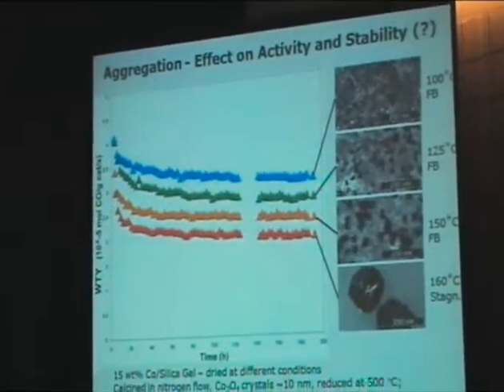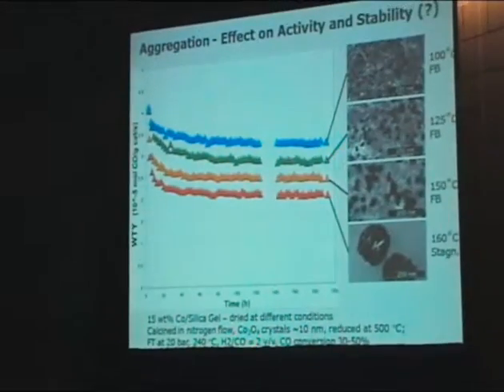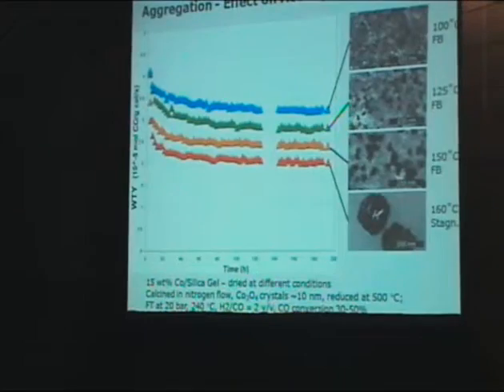Well, since we applied a quite severe reduction, this may be an impact via the reduction rather than the catalysis. However, it also seems that the most significant deactivations are apparent with the catalyst with the lowest activity. And that's something that intrigues us, and therefore we now study more extensively the deactivation behavior of these different systems.